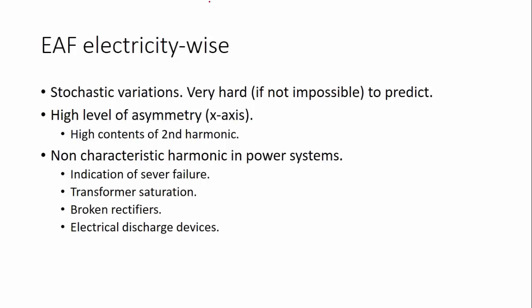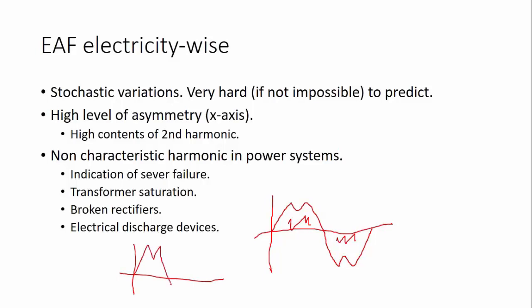So one of the main characteristics of the arc is that it's highly asymmetrical with respect to the x-axis, which means that even though you may have a high degree of distortion, in a normal load you have x-axis symmetry. But in an arc furnace, you can have a very asymmetrical load, which can be something like this. This has a high degree of asymmetry. When you have asymmetry with respect to the x-axis, you have second harmonic.